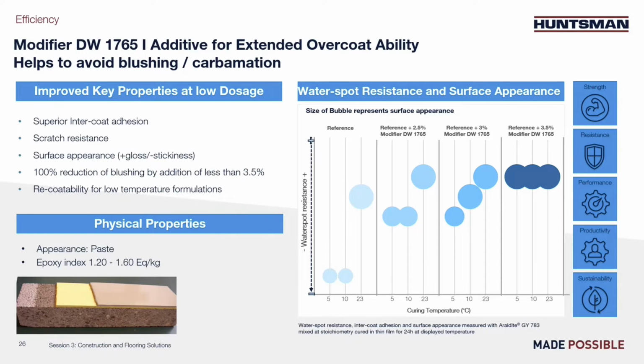On the graph, you can see the effect on a very bad reference with bad water spot resistance at 5, 10, and 23 degrees. Adding 2.5% reduces considerably the surface defect, and with 3.5%, the surface is kind of perfect, even at 5 degrees. So the modifier 1765, I would say it's a good way to improve a formulation without changing it. So without changing hardener and resin, it's more like a drop-in. That's the advantage.